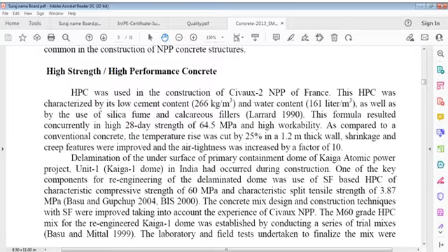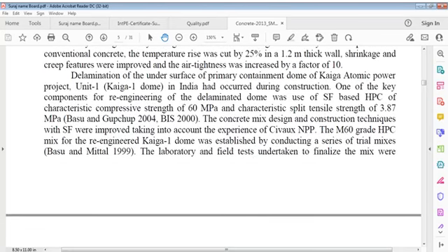Delamination of the dome of Kaiga Atomic Power Project Unit 1 in India had occurred during construction. One key component of re-engineering of the delaminated dome was use of SF based HPC, silica fume based high performance concrete, of characteristic compressive strength 60 MPa and characteristic split tensile strength 3.87 MPa. Concrete mix design and construction techniques where silica fume was used were improved, taking into account experience of Civaux NPP. M60 grade HPC mix for re-engineered Kaiga 1 dome was established by conducting a series of trial mixes.